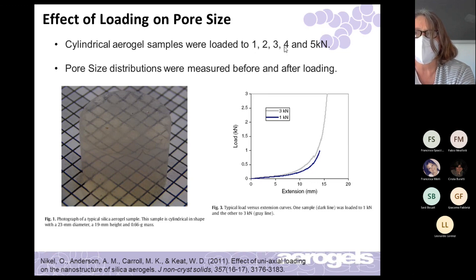And we looked at pore distributions using gas adsorption, the thing I was talking about yesterday, to look at what's happening to the pores as you do that. And here are some, this is not stress versus strain, but it's related to stress versus strain. This is the actual load, and this is the extension, how much you move down. And we can convert this to stress strain, but I didn't.